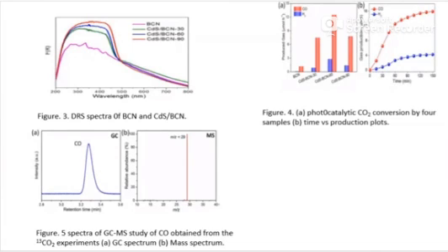So from the depicted graph, the peak appearing at 3.27 minutes in GC spectrum, the figure 5A, having the mass charge ratio of 29 in MS spectrum, directly belongs to the CO. So from this, it confirms that our composite material is reducing the supplied carbon dioxide efficiently.